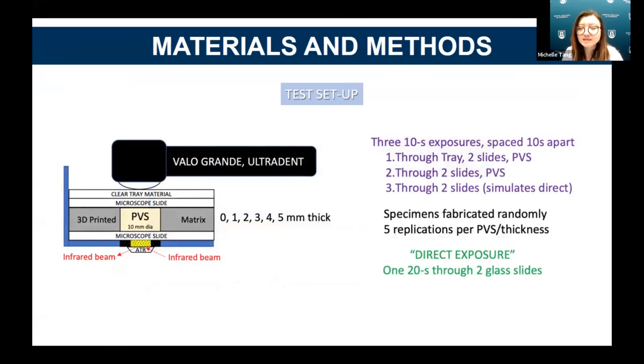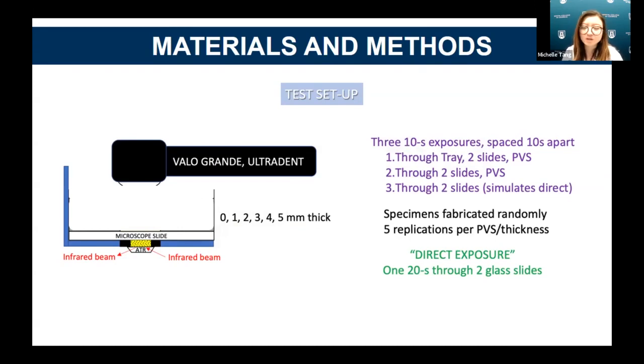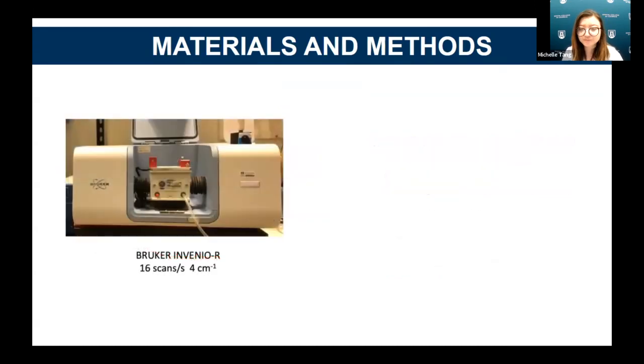Light exposure was conducted in 3 intervals of 10 seconds each to simulate the clinical scenario. The initial light exposure was through the entire setup. The second light exposure removed the tray, and the final light exposure removed the PVS material with the intention of simulating direct exposure intraorally. 5 replications per thickness of material were conducted. A direct exposure of 20 seconds through 2 slides was used as the control group.